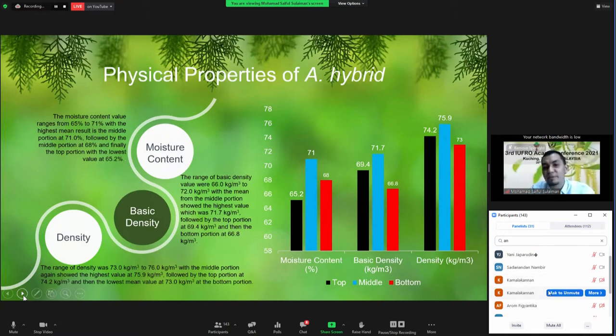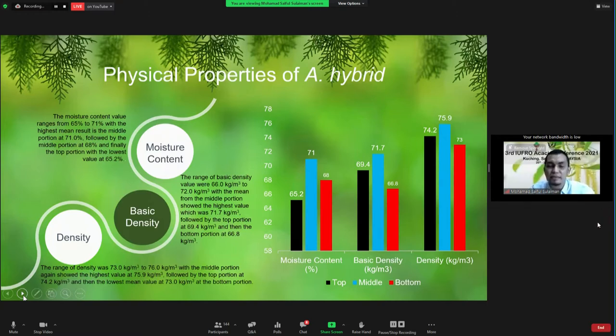So the figure represents the green samples, which had a moisture content ranging from 65% to 71% at the different portions, as represented on the graph below. And the basic density and density highlighted different ranges of value, with a basic density of 66 to 72 kg per meter cube, and the density ranging from 73 to 76 kg per meter cube at the bottom, middle and top respectively. We found that the highest value is at the middle portion, as shown in the figures on the slide, right?